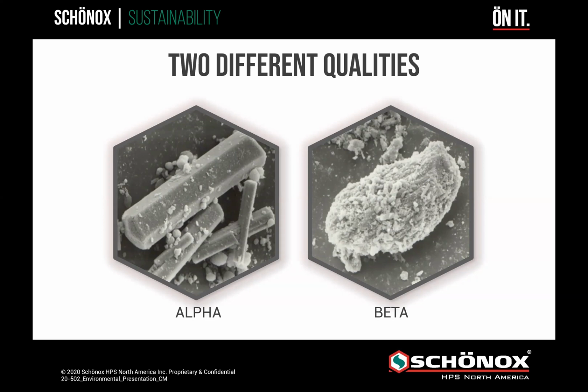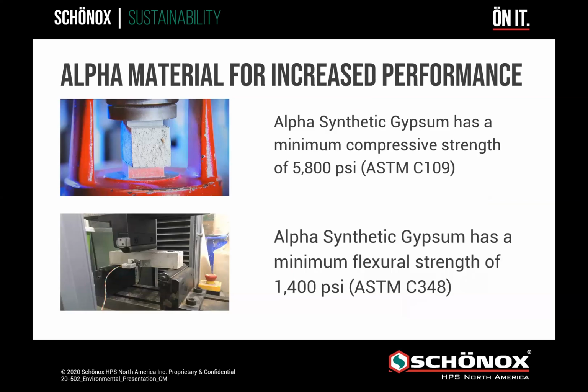When the pressure is released in the autoclave, it will become beta shaped. Beta shaped is amorphous, kind of like a Q-tip. So it will not give you the same compressive strength and flexural strength as you would with alpha. Schönox has the only facility that will produce 100% pure alpha particles in the production of our material.